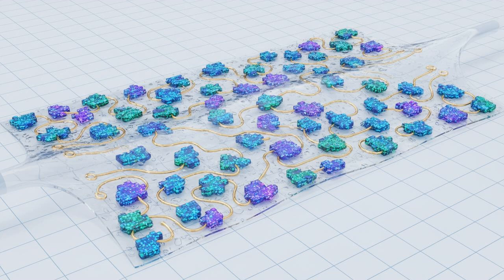You cannot simply run a straight wire between these islands. It would snap immediately upon stretching. Instead, engineers use serpentine interconnects. Imagine a spring. A straight metal wire is stiff, but if you coil it into a spring, it becomes stretchable. Serpentine interconnects work on the same principle, but in two dimensions. They are metal traces, patterned into fractal, S-shaped, or horseshoe curves. When the display is stretched, the islands move apart, and the serpentine wires simply uncoil, effectively straightening out without actually stretching the metal material itself. The strain is absorbed by the geometric change in shape, not by the deformation of the atomic lattice.